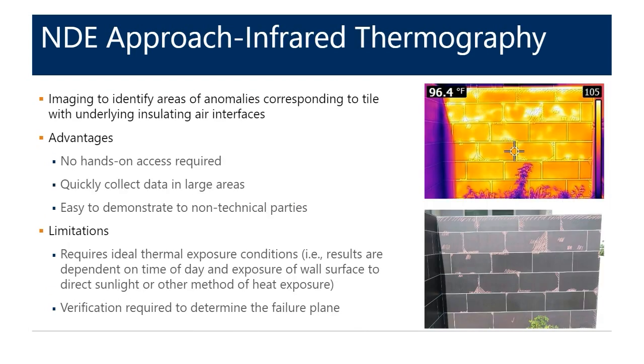For many NDE projects, it's a good idea to apply multiple test methods as a verification of results — if we get good redundancy in findings between two methods, that adds confidence. In some areas where we did acoustic sounding, we also used an IR camera to produce thermograms of the cladding surfaces. Due to the importance of ambient conditions, this method was most effective on east-facing building elevations with direct sunlight exposure within a few hours of sunrise. On other elevations and times of day, the differential between surface temperatures in sound and unsound areas was just not as apparent.